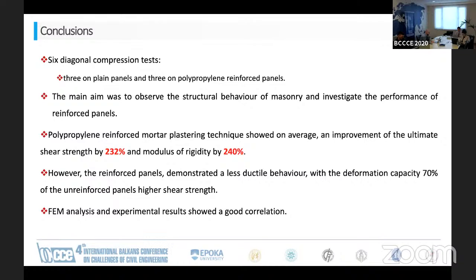So to conclude, we did 6 diagonal compression tests, 3 on plain and 3 on polypropylene reinforced panels. The main aim was to observe the structural behavior of masonry and investigate the performance of reinforced panels. The polypropylene reinforced mortar plastering technique showed on average an improvement of ultimate strength and the modulus of rigidity. However, it demonstrated a less ductile behavior with a deformation capacity of 70% of what the unreinforced panel had.